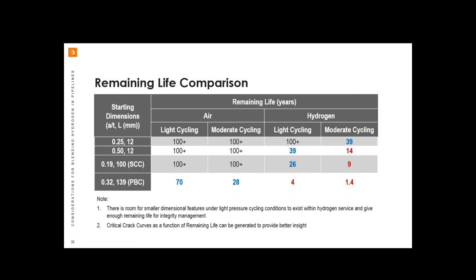This slide provides you with a comparison. The previous graphs didn't have the light cycling on them, simply to make it less busy, but here we'll note the remaining life in air versus hydrogen for light cycling and moderate cycling. So we note that under moderate cycling conditions, those features that we had have very good remaining life. We see the influence of the increased crack growth rates. However, we'll note that under light cycling conditions, we are seeing some amount of remaining life that we may be able to actively manage and operate a pipeline safely. So I think this really shows us that there's room for smaller dimensional features under light pressure cycling conditions to exist within hydrogen service, and that they give enough remaining life for integrity management.